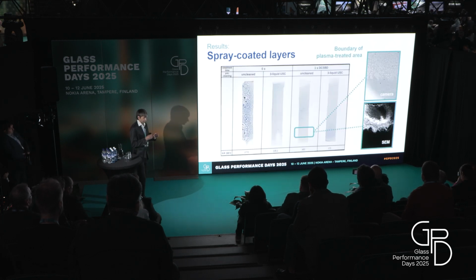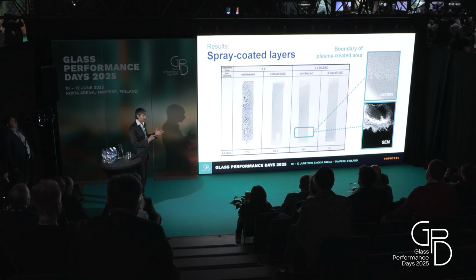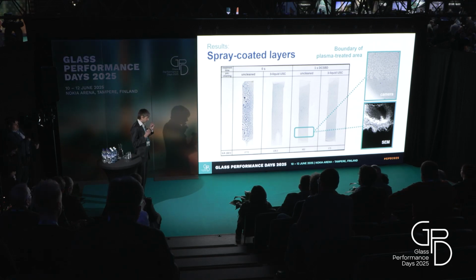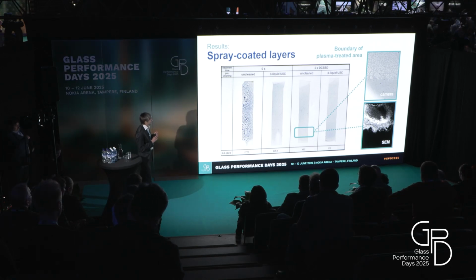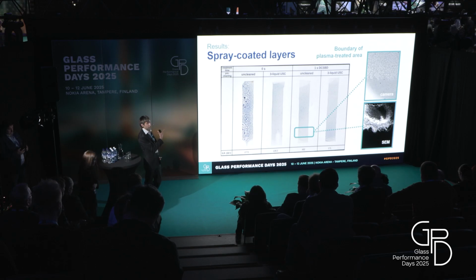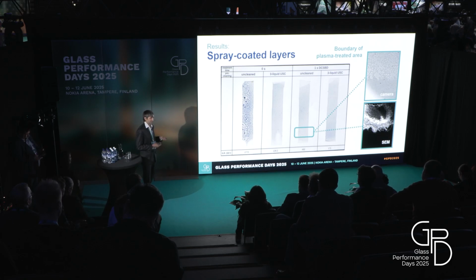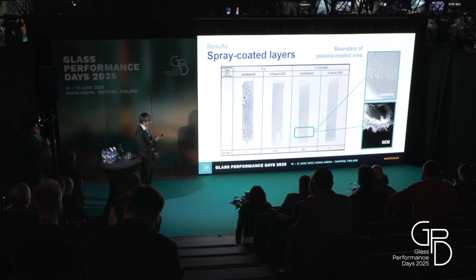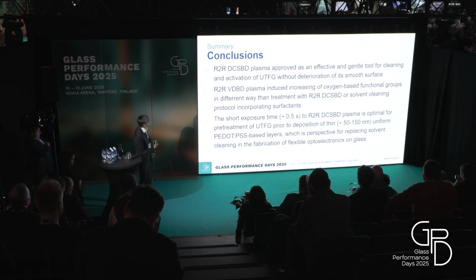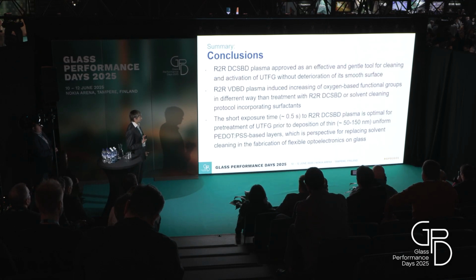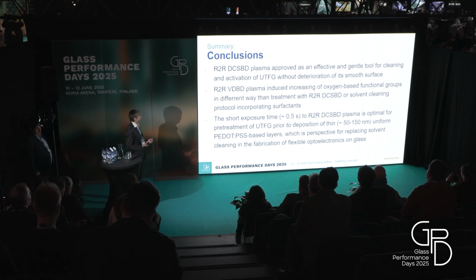Visually, as I was showing you, the papers which I needed to attach the flexible glass on the roll of our cylinder covered the plasma, and we can see the border of this paper on the coating. So I placed the paper in the plasma on the flexible glass during the treatment, and then I made a coating, and it showed that the parts which were covered with this paper were not affected by the plasma. So it's a nice, clean result that the plasma is effective, and it's possible to see it also with the naked eye. And it's not deteriorating the very smooth surface of the flexible glass.